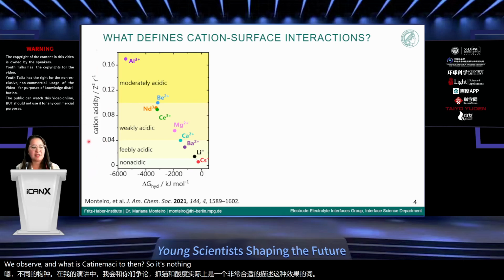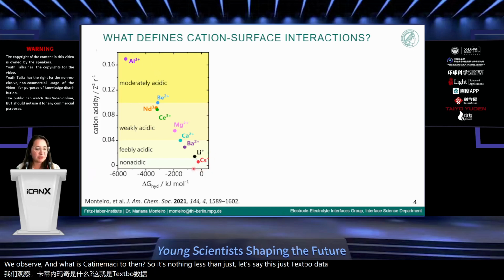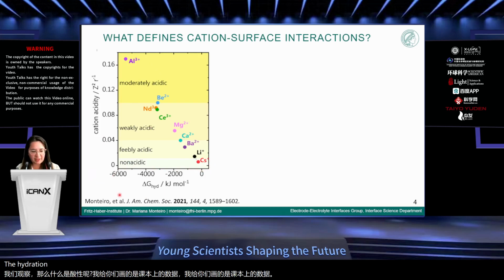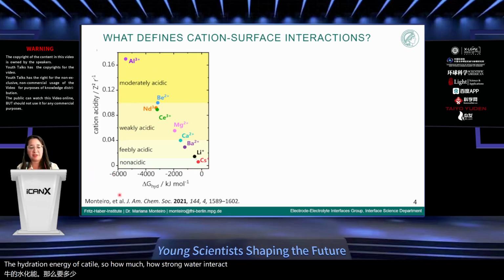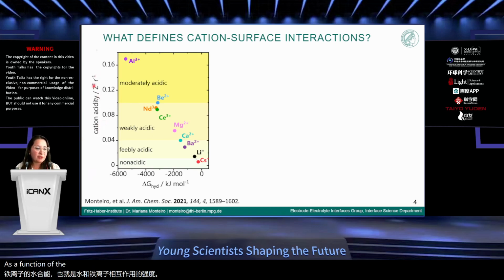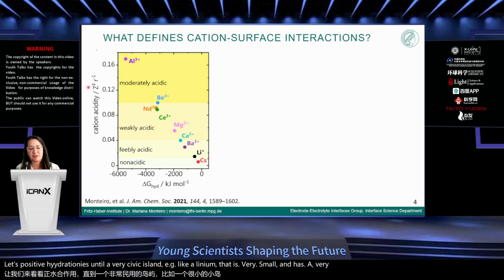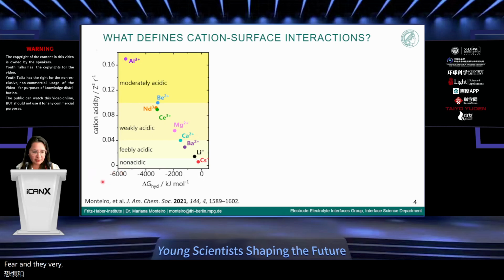This is just textbook data. Here I'm plotting for you the hydration energy of a cation, so how strongly water interacts with this ion, as a function of the square root of the charge over the radius. This is basically a relationship of how strongly water feels the charge and interacts with this positive ion. For the species we looked at, you go from very positive hydration energies to very acidic ions, for example aluminium, that is very small and has a very large hydration sphere and a very, very negative Gibbs free energy of hydration.